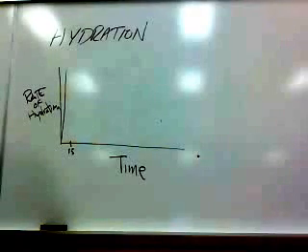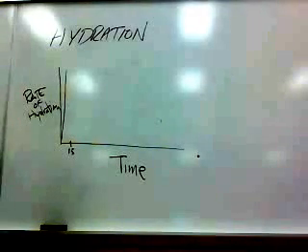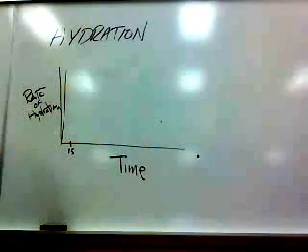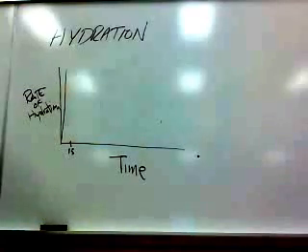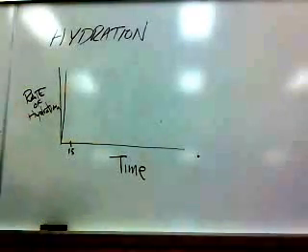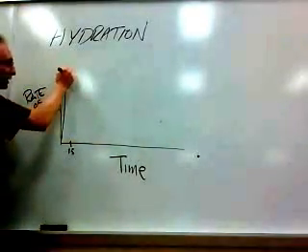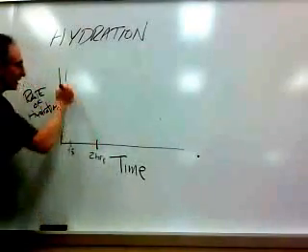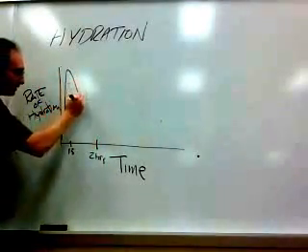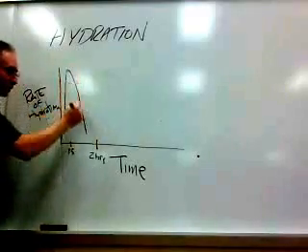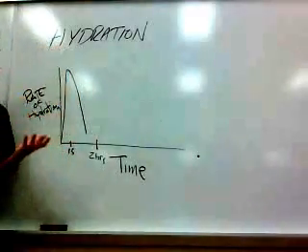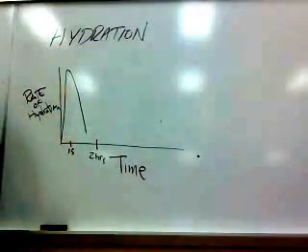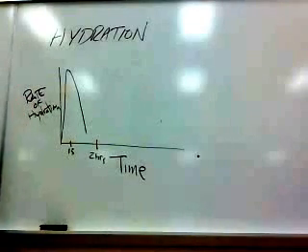Okay? So there's stuff that's hydrating right away, but it's not making it stiff. It's not making it strong. It is hydrating very quickly. But then, for about 2 hours, nothing sort of happens. The rate at which things are occurring just drops almost down to nothing.